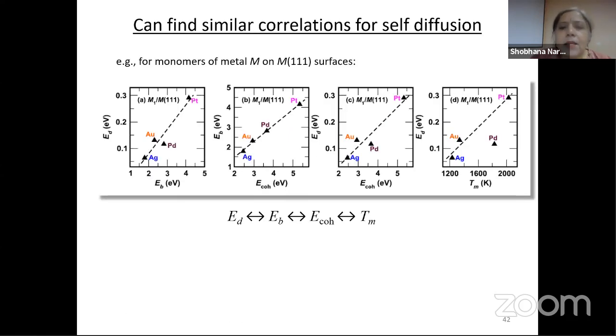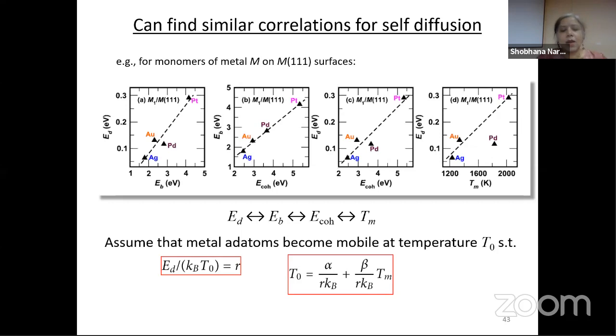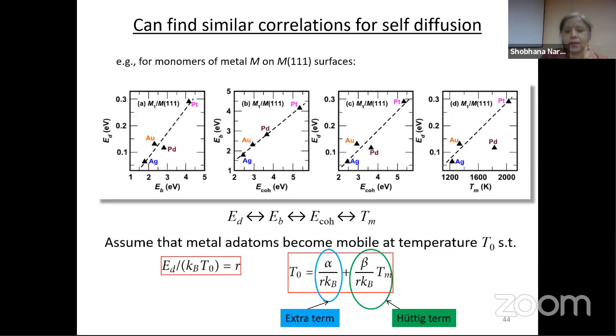Can we show similar correlations for self-diffusion, that is clusters or atoms of a metal on that metal surface? So here I've shown you for single atoms of the metal on the 111 surfaces of these metals. And you see that this correlation holds pretty well, again, for similar reasons. And we can try then to get a mathematical relation that relates the temperature at which atoms become mobile on that surface to the melting temperature. And we get this relation that I have boxed. You get something like this empirical Huttig term, but you have an extra coefficient in front. So we have also rationalized this empirical finding of this Huttig term.